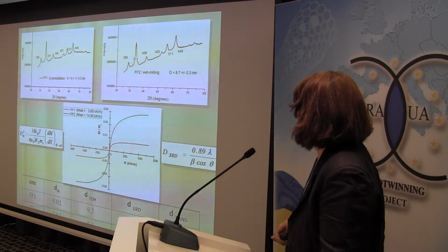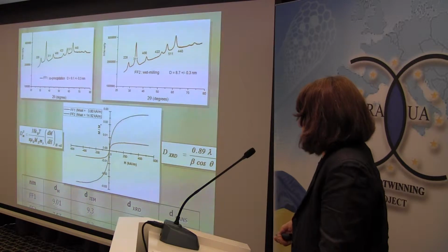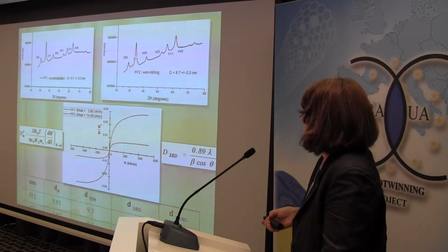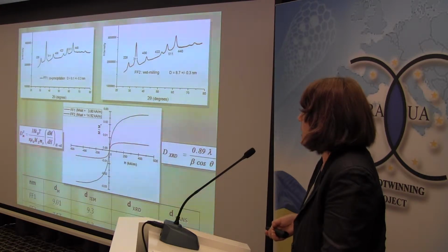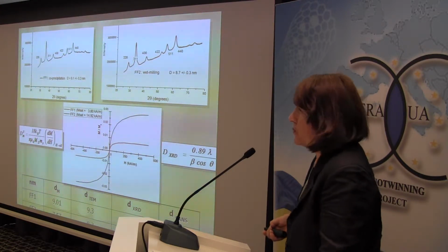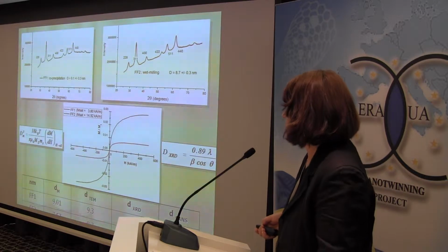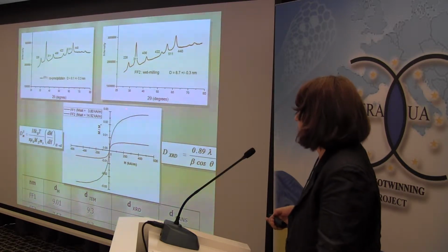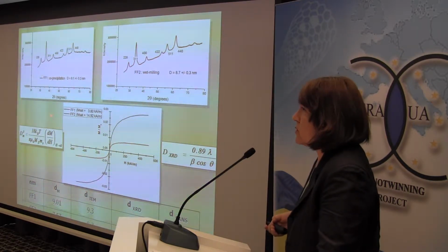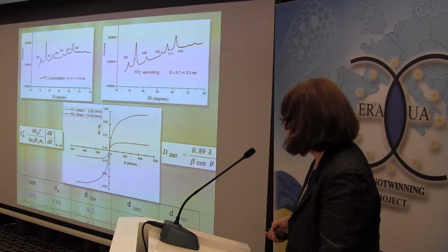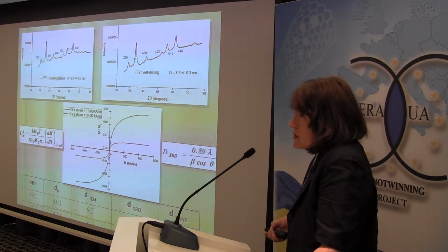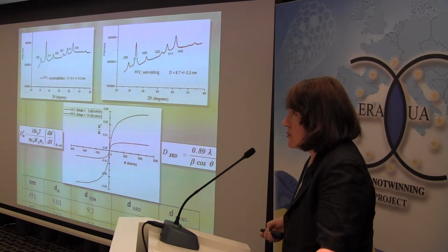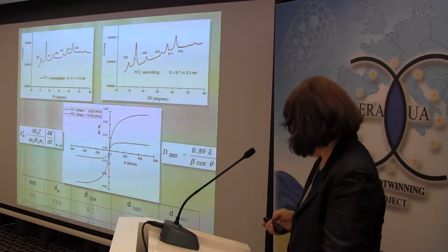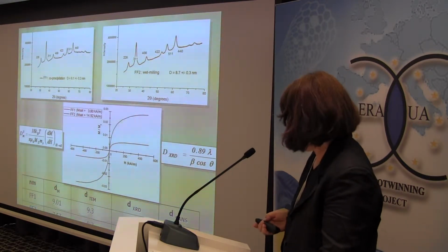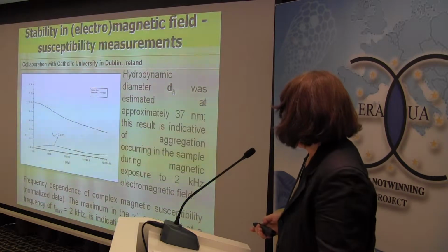The diameter of the crystallite was measured in all cases, and from the magnetization data, the largest magnetic diameter was also evaluated according to Langevin's theory. Higher magnetization was obtained for the wet milling product, and this is of course because during the long milling time a higher amount of ferrophase was incorporated within the fluid.